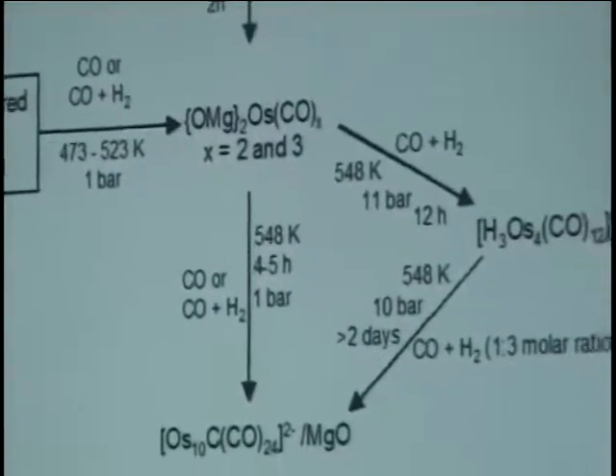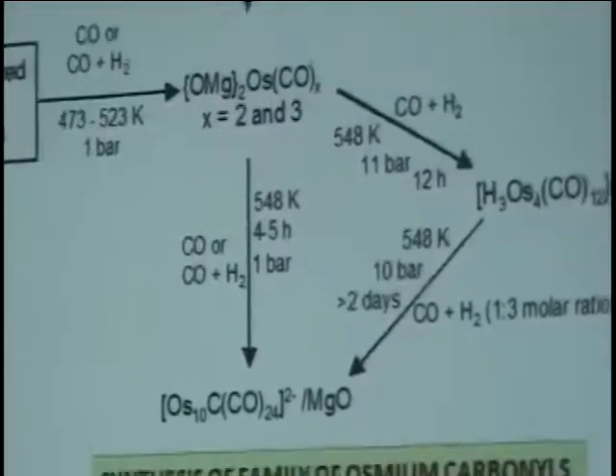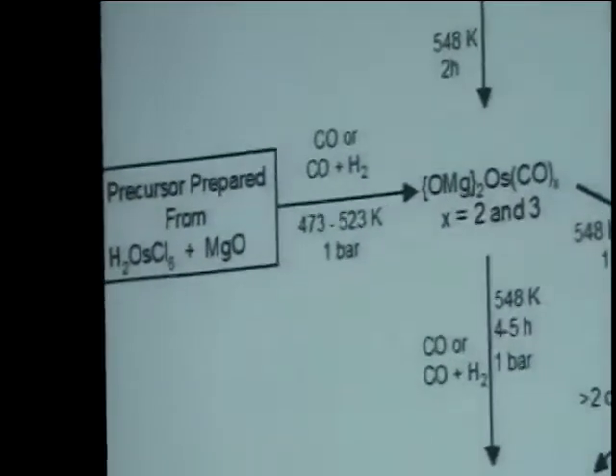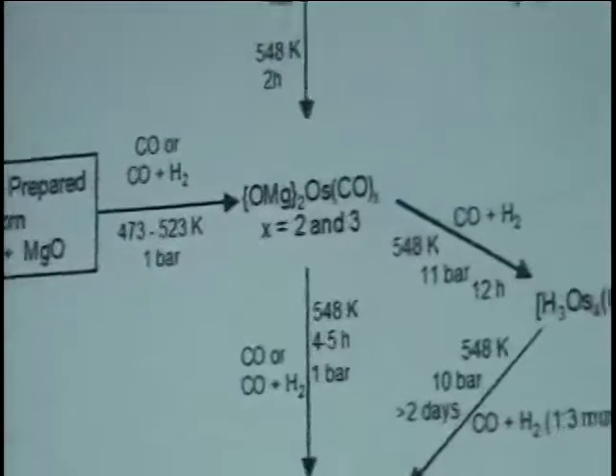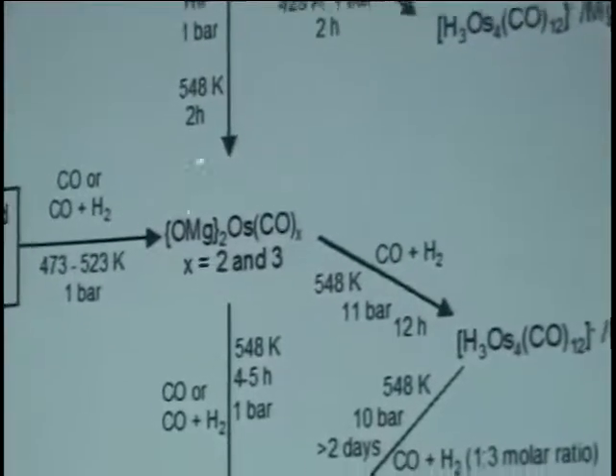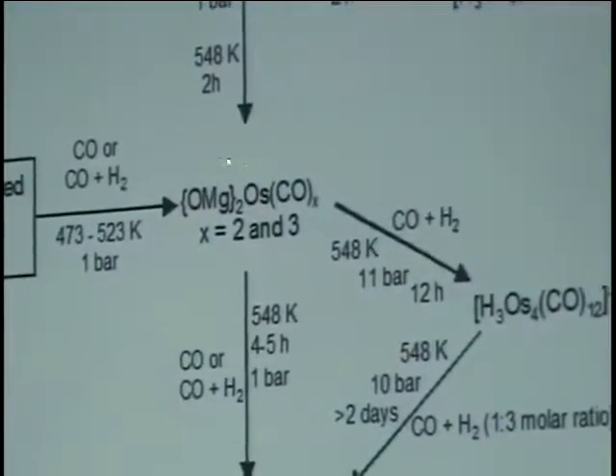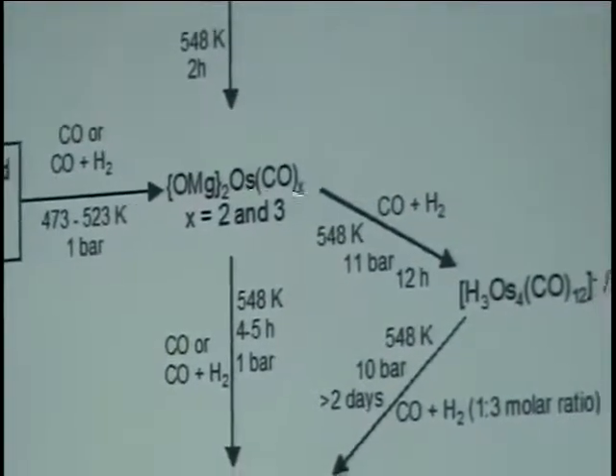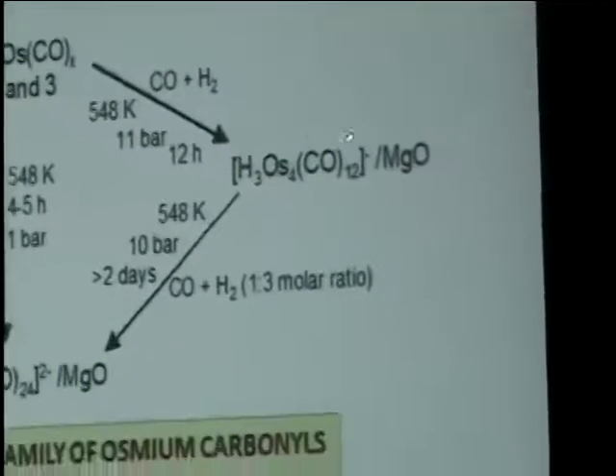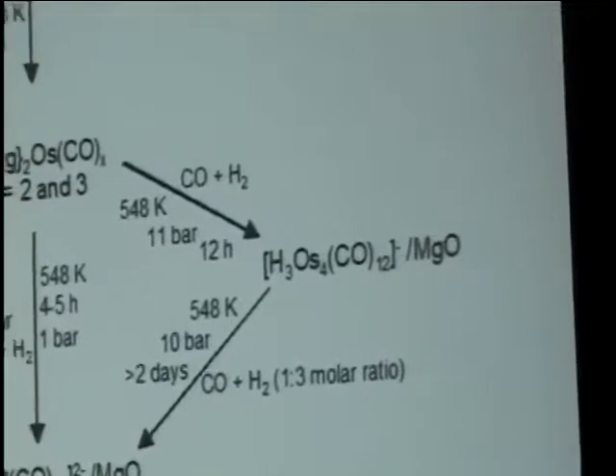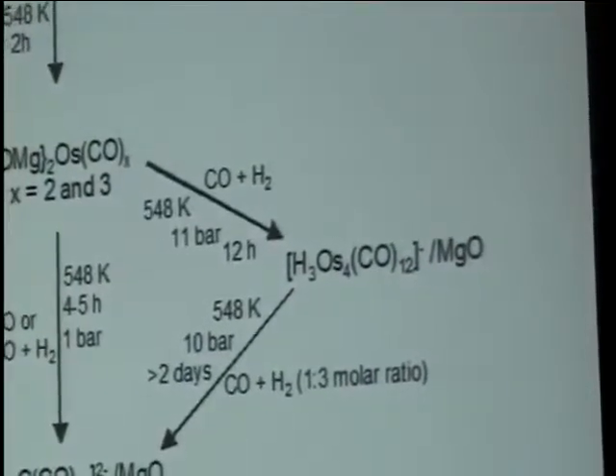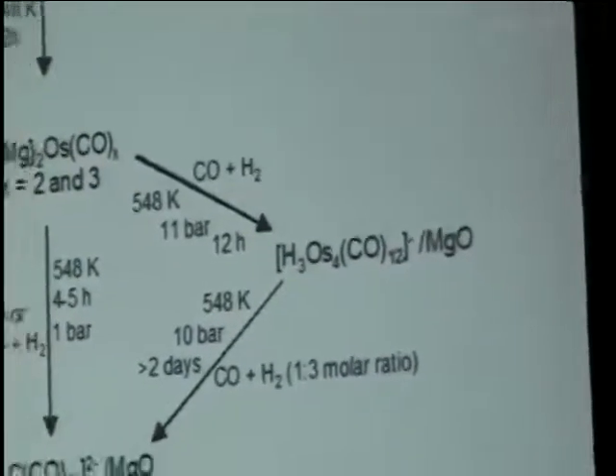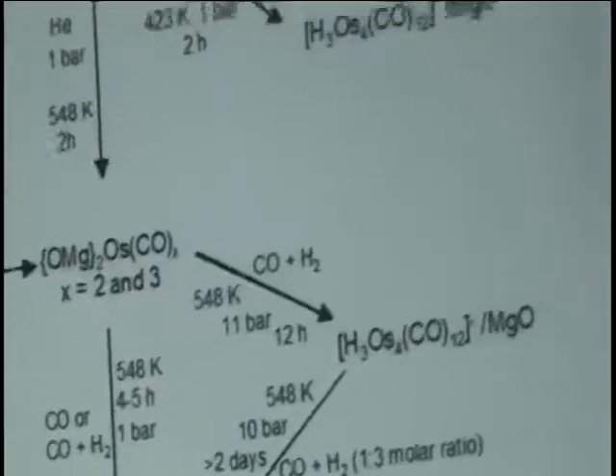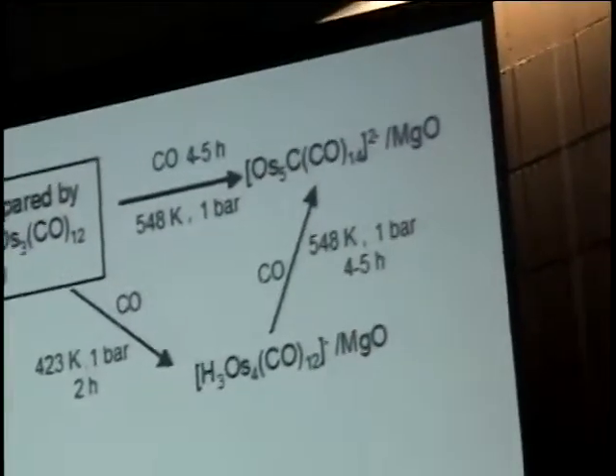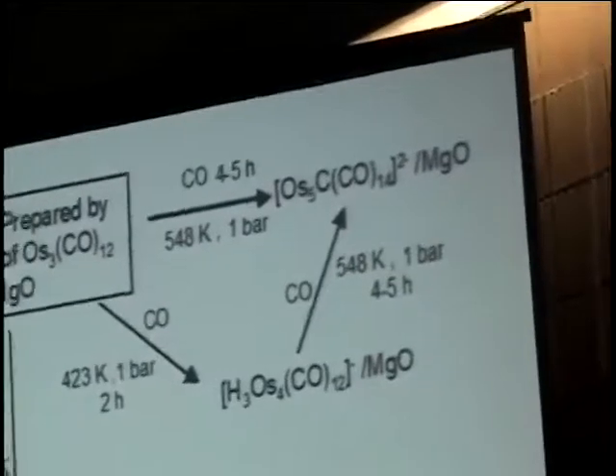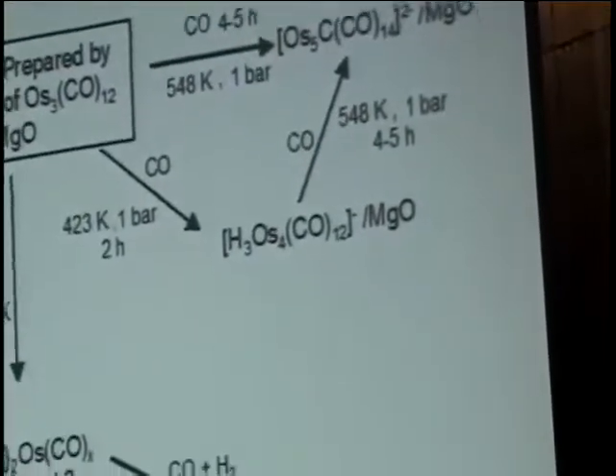And there's lots of work in our literature with rhodium analogs and iridium analogs and so forth of this. Now, with this as a starting point, one can make larger clusters. So one can make the 4-atom cluster, and this is an anion. On the basic support, we get anionic structures. 4-atom cluster, we can go this way. I'm not showing all this. This is chemistry that's been worked out to get pretty high yields of these different species, but it's more complex than this.